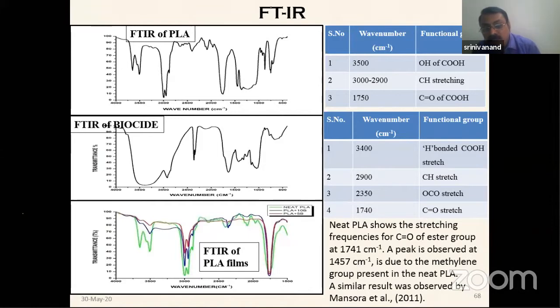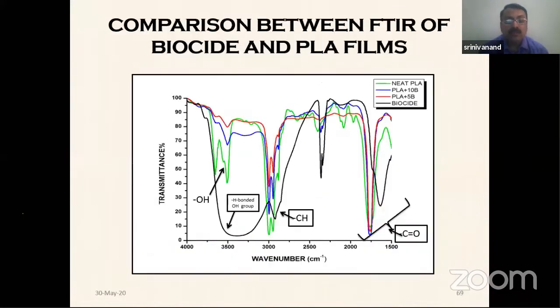And you can see the characteristic peak of neat PLA is due to the carbonyl peak, which comes around 1741 cm⁻¹, and the 1457 cm⁻¹ due to the methylene present in PLA. So when we observe the PLA and biocide, the black one corresponds to biocide, whereas the green one corresponds to neat PLA. Blue one is PLA with the 10% biocide loaded, and red one is PLA with the 5% biocide.